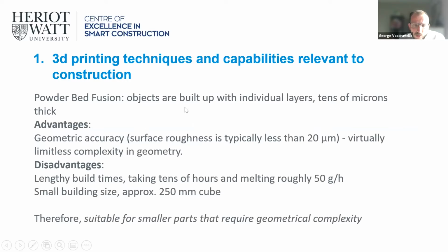This technique offers the advantages of geometric accuracy. The surface roughness is typically less than 20 micrometers, so a very smooth surface of the component that is 3D printed. And essentially, there is virtually limitless complexity in geometry. So we can 3D print metal parts that are as complex as we like. There is no limit in the complexity.